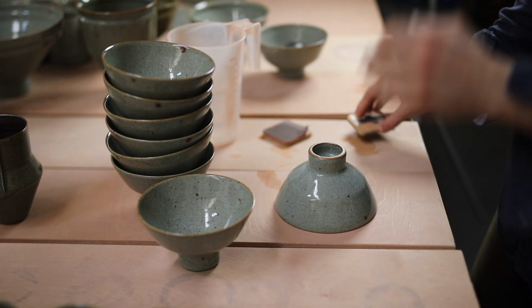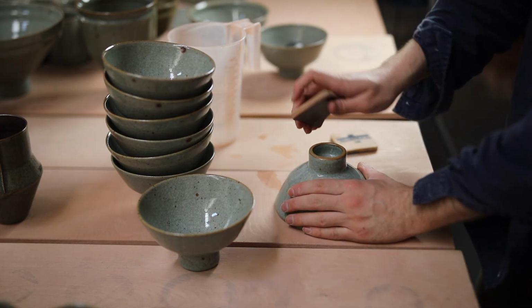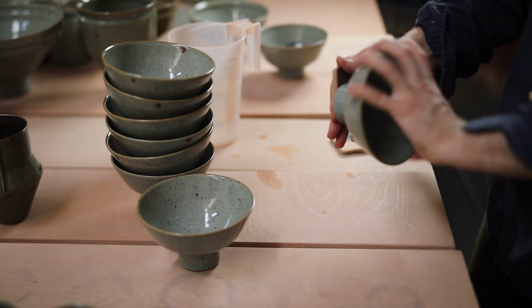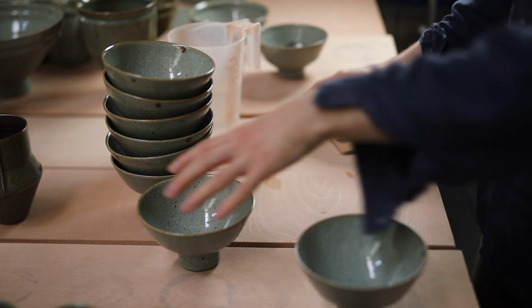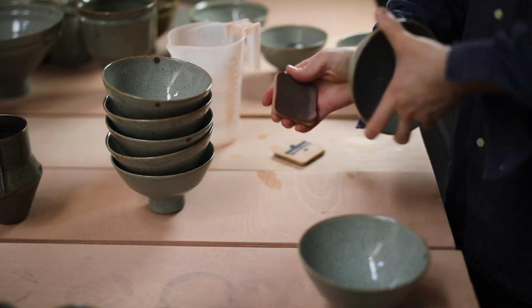The next thing I have to do is grind the bottom of each, as during the firing the clay body shrinks around the coarse particles of grog contained, and so these sharp specks need to be softened, which I do with some wet diamond pads made by Diamond Core Tools.